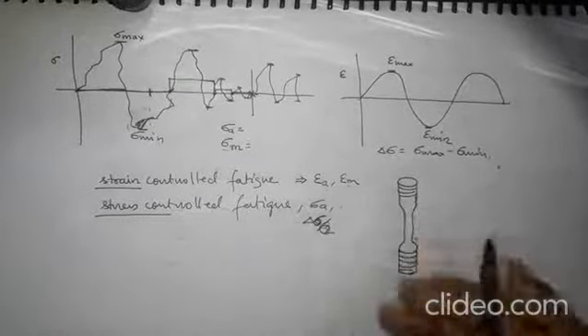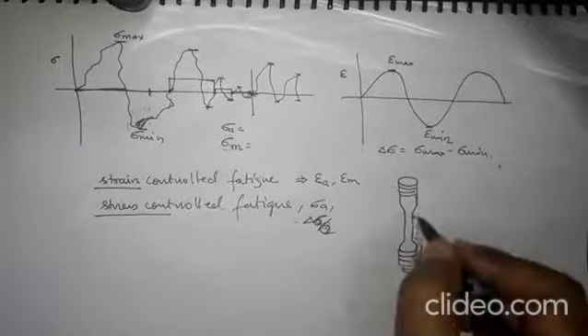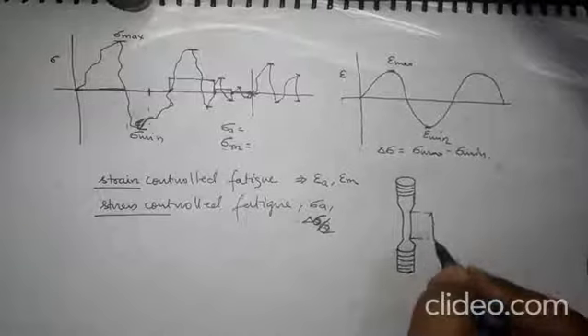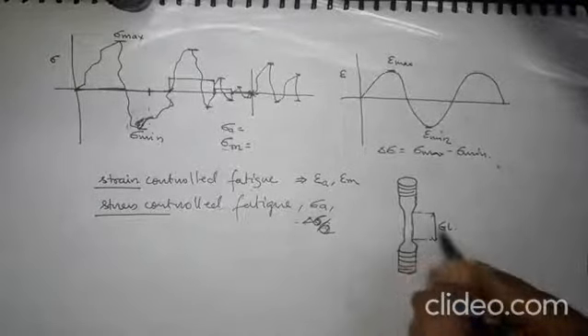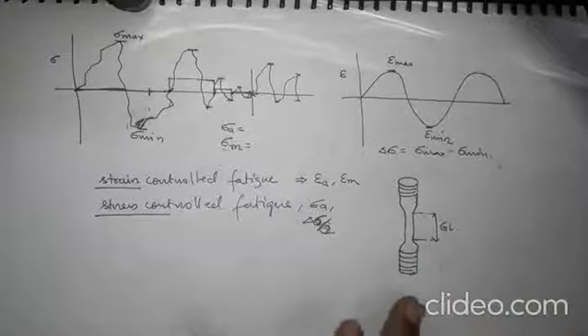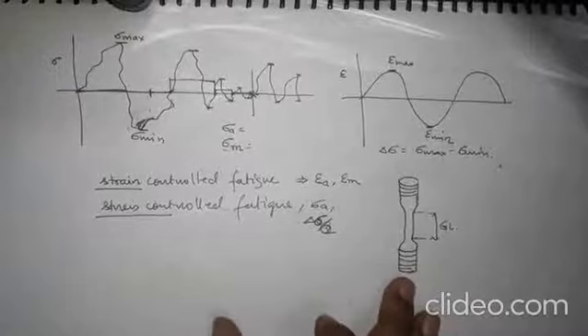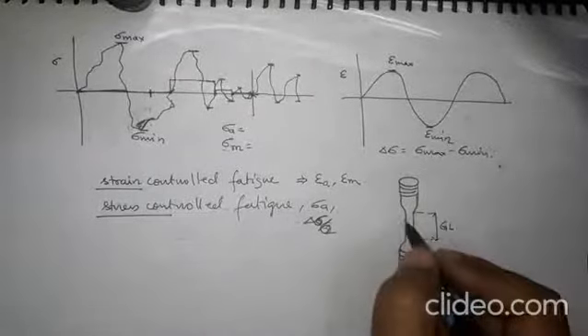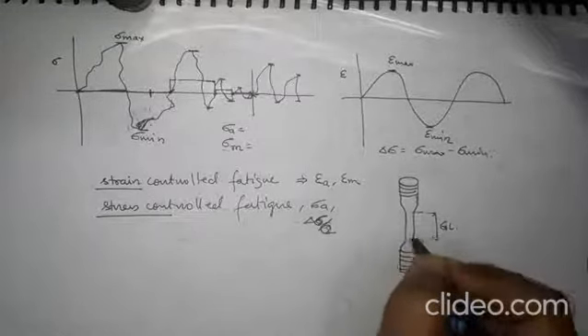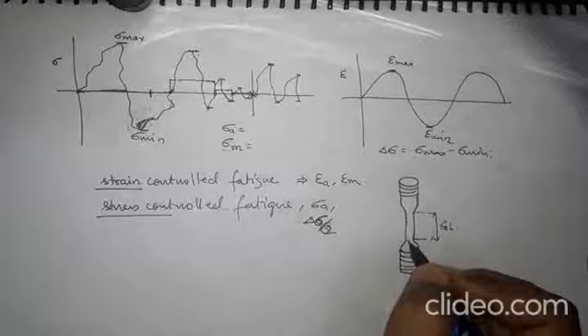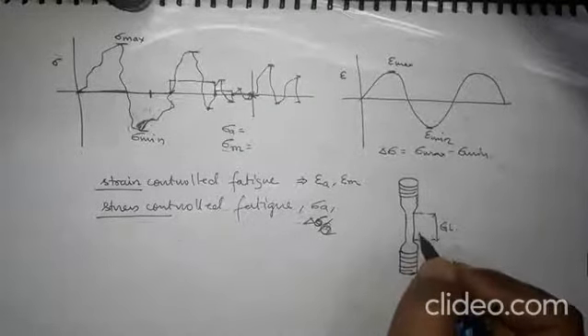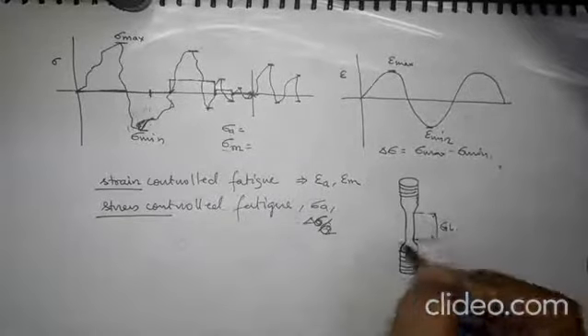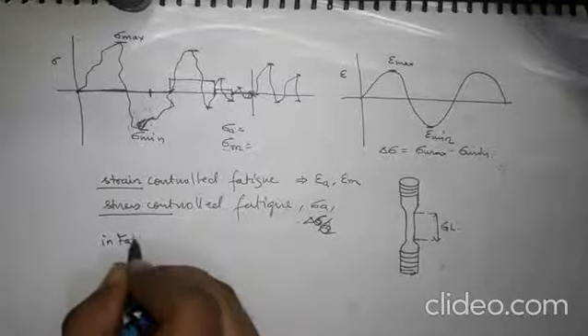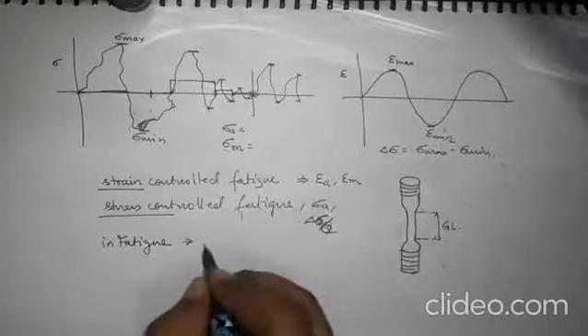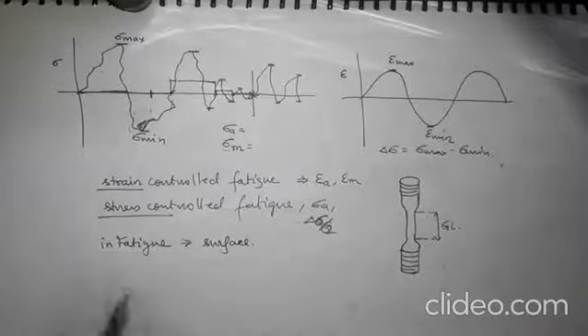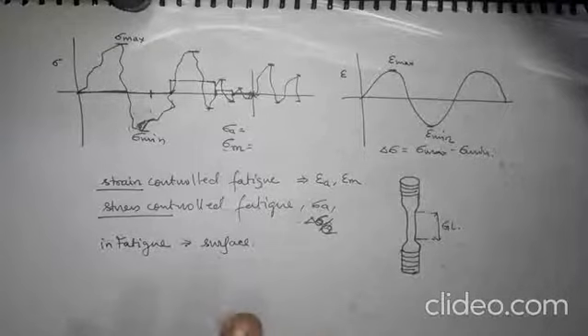Okay, so you put the upper part in the machine, put the lower part in the machine. So this is your gauge length again, and then you can measure the diameter also. The difference between a tensile test specimen and a fatigue test specimen is that before doing the test you polish the surface of the specimen to mirror polishing level, usually for metallic materials. The reason you have to do this is because in fatigue the surface is very important. Okay, and we will see why. The damage which happens in fatigue usually starts from the surface.